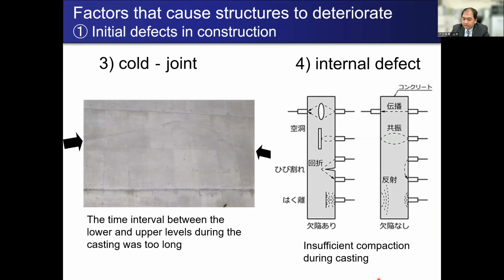The cold joint, what is the cold joint? The time interval between the lower and upper levels during the casting was too long. If the interval time is too long, this kind of cold joint will occur. At the time of casting, if the interval time is too long, then the lower part of the concrete starts hardening. Then even when the upper part of the concrete is cast, the lower part has already started hardening. So this kind of crack will remain. This is a cold joint.